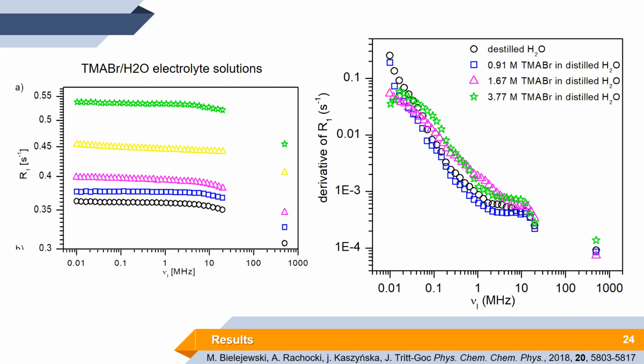Okay, so to explain first why the relaxation rate changes when we add more and more ions. This can be explained in two possible ways. First, the viscosity of the system changes. When we increase the number of ions in the liquid, in the water, then the density of the system also increases. And because of the mutual interactions, also the viscosity of the electrolyte increases. When those parameters increase, the molecular dynamics, the motions, are slowing down. So the dipole-dipole interactions are stronger and thus the relaxation rate is faster, or the T1 relaxation time is getting shorter.